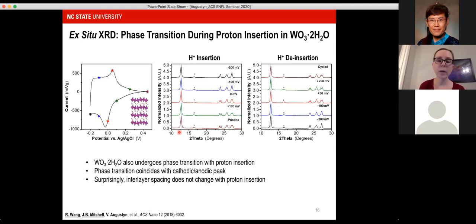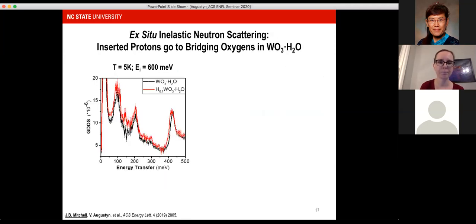And this was surprising to us because if we expected a proton to be bonding at a terminal oxygen, we would expect to see changes in the tungsten-oxygen bond lengths along that axis. So the fact that we didn't see that was really surprising to us at the beginning.